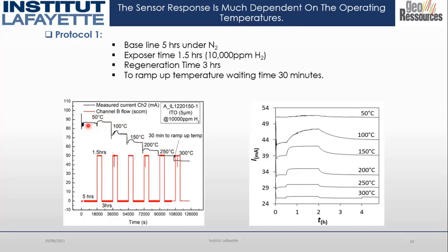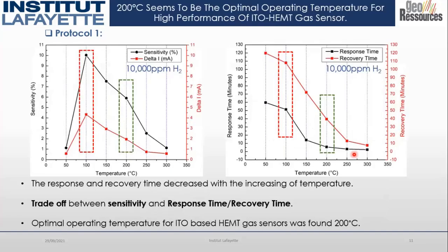We can see from here that with the increase of temperature, the baseline of the sensor was decreasing. So this is the magnified version of the output response at different temperatures. It's very clear that our sensor response depends much on the operating temperature. So we can see two curves here, the sensitivity versus temperature. At the beginning, the sensitivity increased with the increase of temperature, but after a certain point, it dropped again. The other one is the response and recovery time versus temperature. With increasing temperature, the switching speed of the sensor decreased.